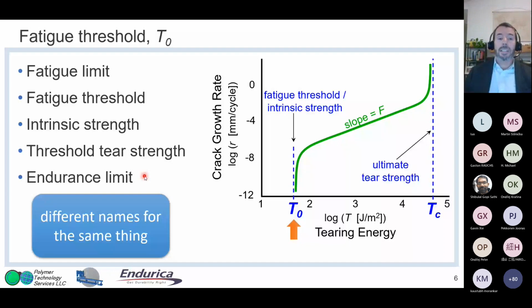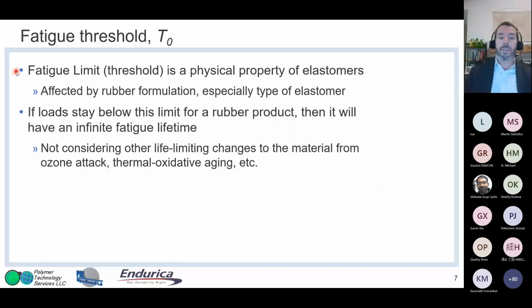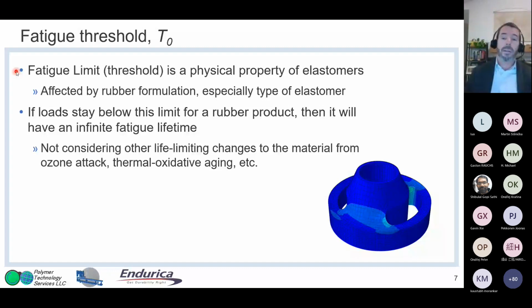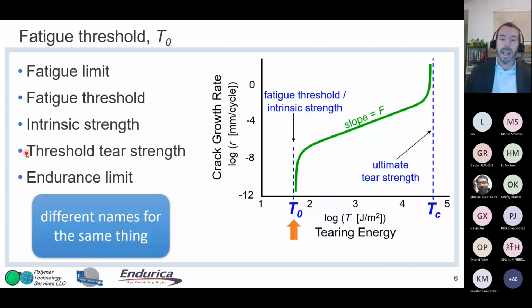So it is a physical property of elastomers, and it is affected by rubber formulation, as you'll see later, especially the type of elastomer. And as I mentioned, if you can figure out a way to make a rubber part operate below this limit, then it can have a very long fatigue lifetime. Again, not considering other life-limiting changes to the material. So you can see why this is a very important parameter, but it's also potentially difficult to measure because it's happening at very, very slow crack growth rates is where this shows up, meaning potentially long experimental time frames.